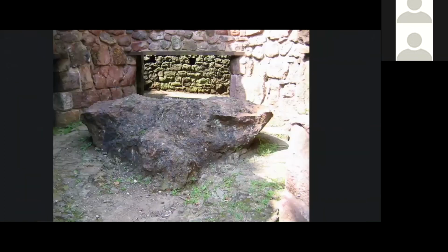But what I can show you here with this furnace that's been partially demolished is the actual iron. This is called a salamander. This is what's left over when you take a blast furnace out of production. The furnace is not actually tapped, which is what they call the process of removing the iron, like tapping a keg. You tap the iron out of it. It's not actually done at the very lowest level of the furnace, so there's usually a couple of feet or more of actual liquid iron beneath that.